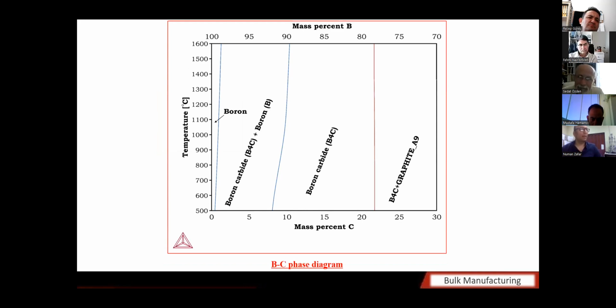This is a boron and carbon phase diagram, nothing overwhelming here, even at 1600 degrees centigrade. These are the ratios which I have used. Even at 1600 degrees centigrade, nothing much is happening here because they are small atoms and they are covalently bonded.